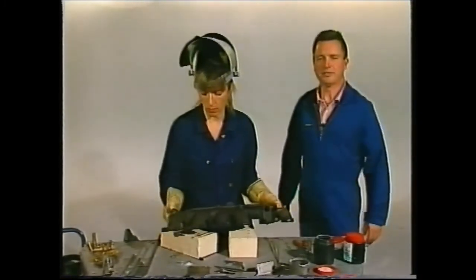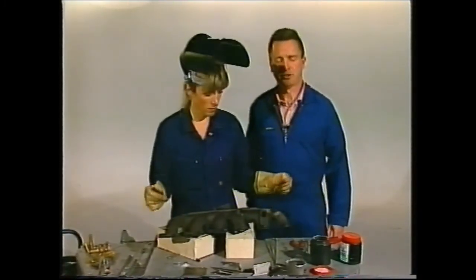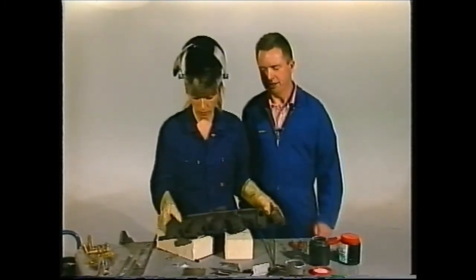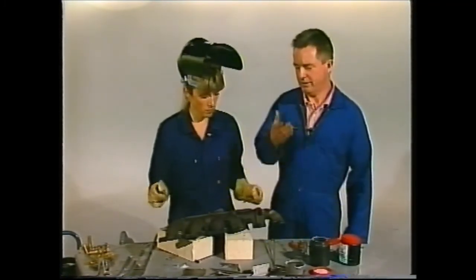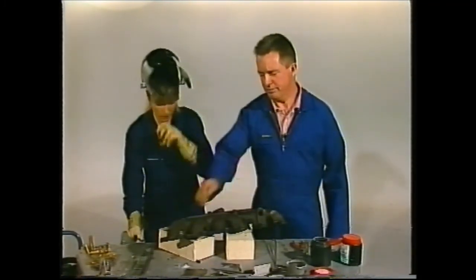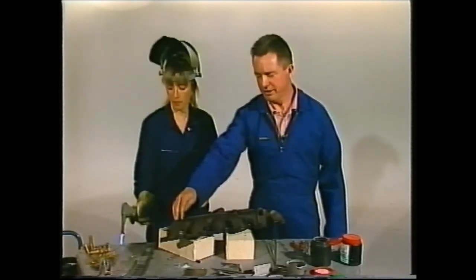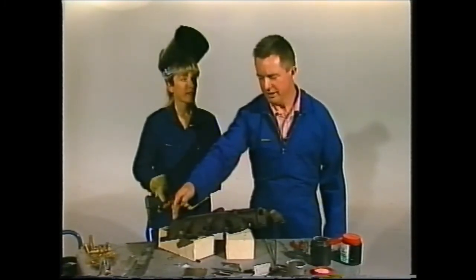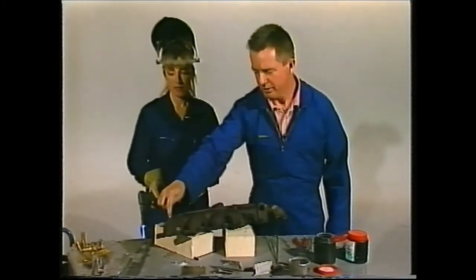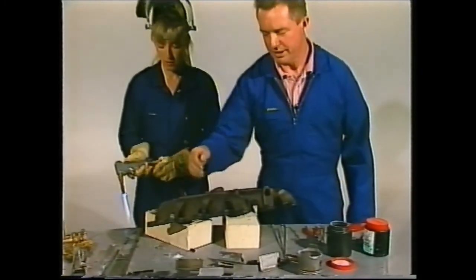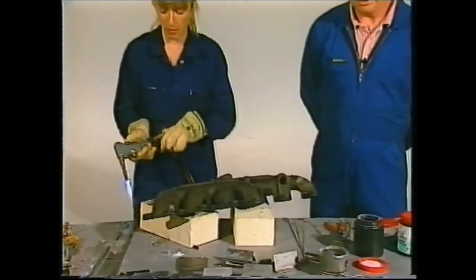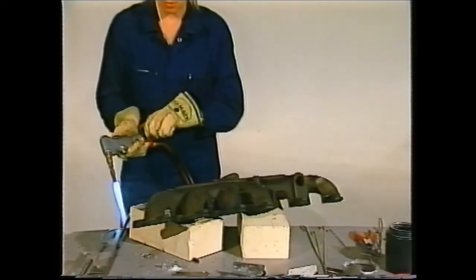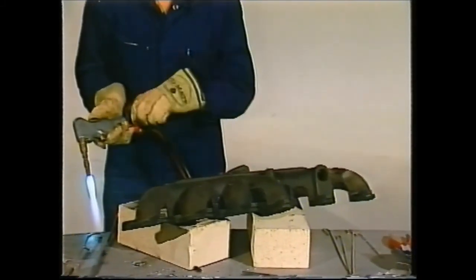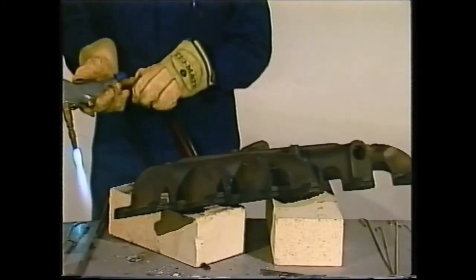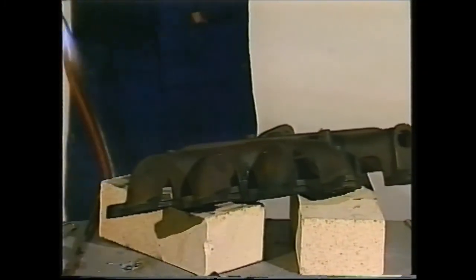Okay, we're now going to demonstrate some cast iron and the torch's unique ability with cast. Now, it requires no preheating or just a slight warm up of the area. Say, for example, there was a crack in here. Lim will simulate this by blowing a hole in it and welding it back up again. Now, to do this, you would turn the torch up to actually blow the hole, and as you'll see, turn it down again to do the actual repair.